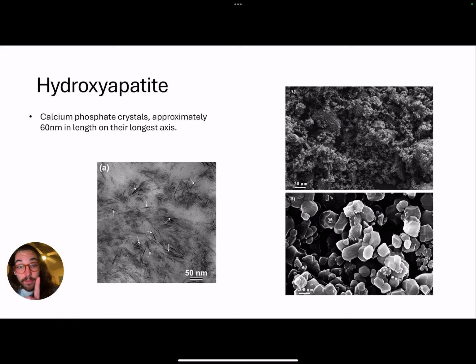Now, I'm mentioning that for a reason, because that was a question in the biomineralization community that was in need of some reconciling. How are these crystals bigger than the holes that they occupy? How are they bigger than the spaces that they're supposed to get through to get there? And this is what came up with the theory that osteopontin is gathering it and producing this liquid-like metastable phase that can be deposited onto the collagen and then subsequently mineralized inside of the gap region of the collagen fibrils. This is the working theory, at least, for many in the biomineralization community.